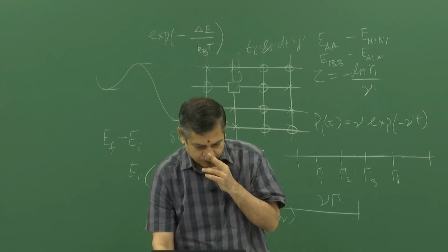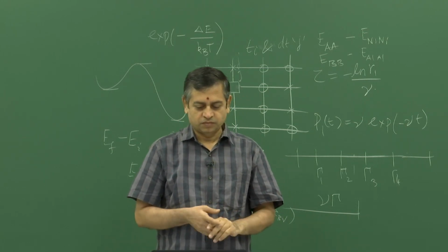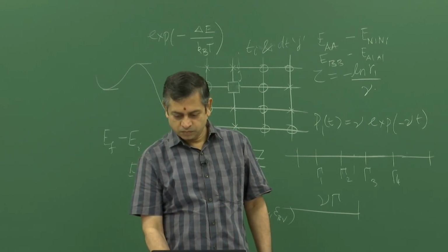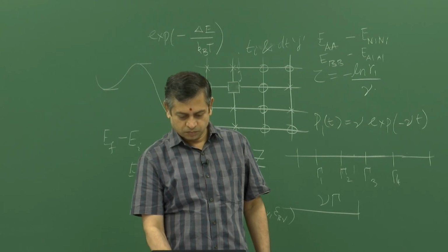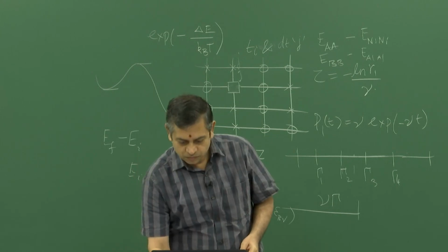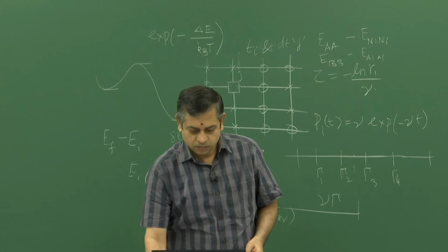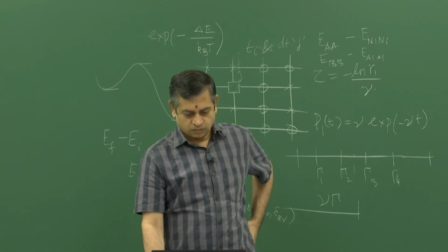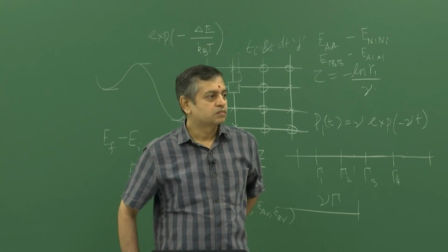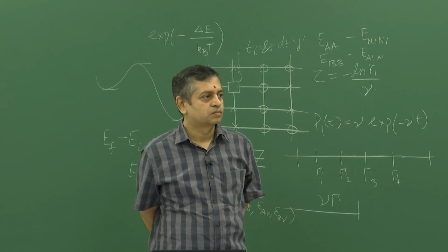Yeah? So here in this square lattice you have 4 possibilities, on an FCC lattice you will have 12 possibilities. For these 12 possibilities you calculate for each of these the respective probability. This is, I think, P_j or so. Now if you think of AB exchanges somewhere in the lattice, you don't have 12 possibilities, but if you have 1 million atoms, you have 12 million possible changes, if you have 12 neighbors.